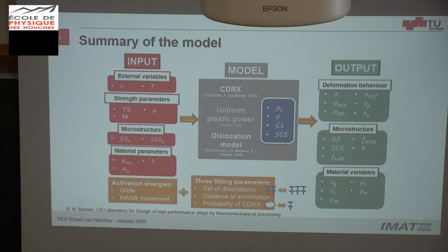For the model, we need as input the external variables and the strength parameters. We are still not in a position to calculate yield strength. We also need the initial microstructure and initial material parameters, activation energies, and high angle grain boundary mobility. The outputs are all these here. It's not only the stress strain curves, it's also the microstructure, the recrystallization rate, and the fraction of high angle grain boundaries. We also have some glide and climb velocities as material variables. Again, we use the continuous dynamic recrystallization model of Montheillet, combined with the Gourdet-Montheillet equations from creep and uniform plastic power.